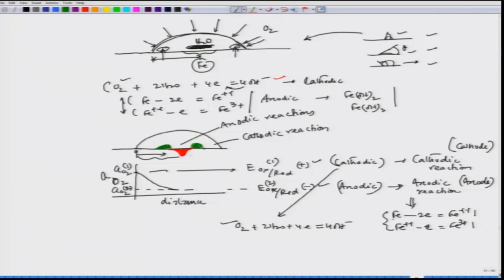So, the corrosion is taking place in the center part, and the cathode regions will have very little corrosion because preferentially cathodic reactions are taking place. And why does it become cathodic? Because we have these situations. So, it becomes a concentration cell where this is the negative part and this is positive and this is positive. So, this is a typical corrosion phenomenon happening inside a water droplet. Even though this water droplet is staying only momentarily, still these corrosion reactions can take place.